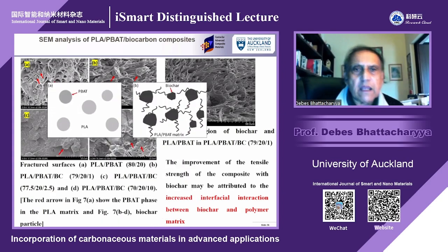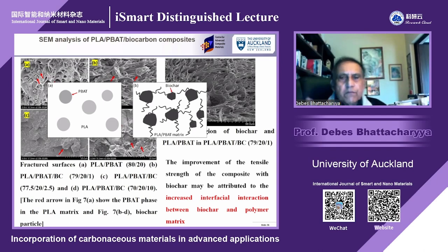And then essentially the schematic diagram: PLA, PBAT are floating, and biochar is there, and we are trying to create some sort of functional property. The biochar normally is very inert. You don't get any functional property created on that. But if you control the temperature, high temperature biochar, normally we make biochar at 750-900 degrees C, but we are using a tube furnace here. We are going to a very high temperature, about 1200-1400 degrees C.